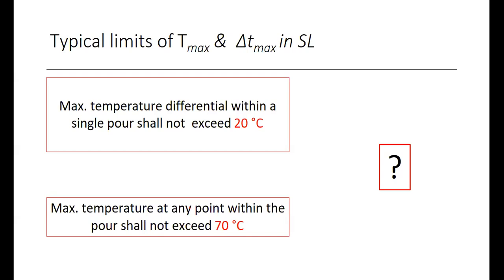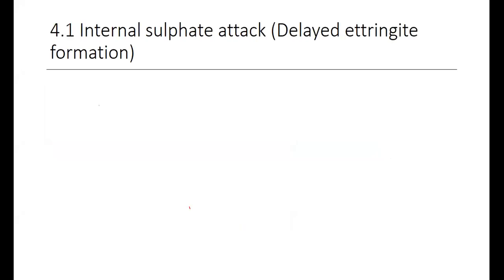In the specification, it says the difference has to be less than 20 degrees, and the maximum temperature, usually the core temperature, has to be less than 70. We'll discuss the engineering fundamentals of these two conventional limits.